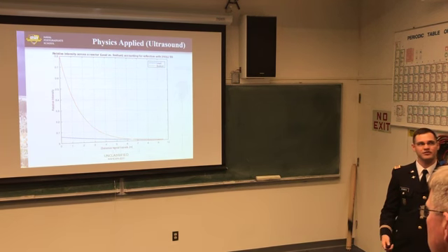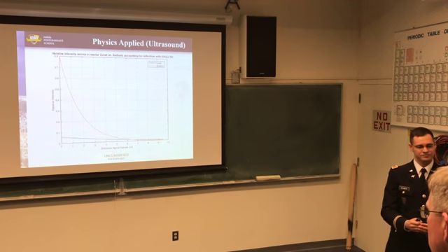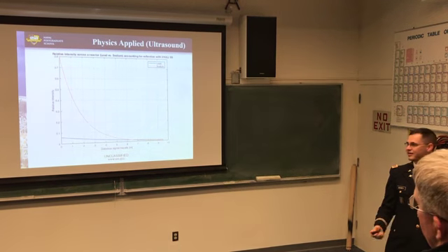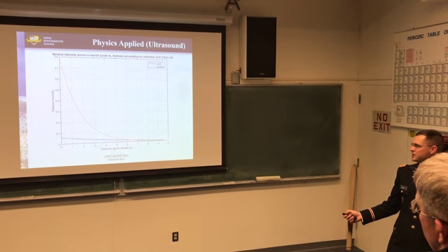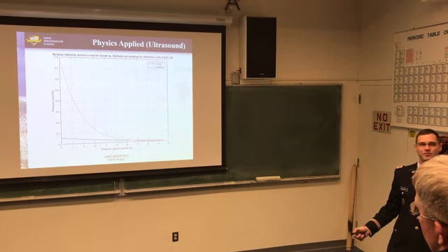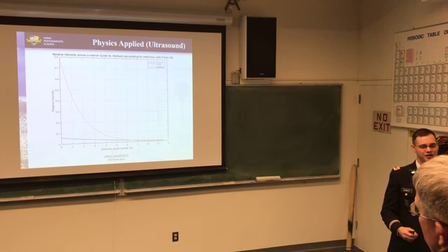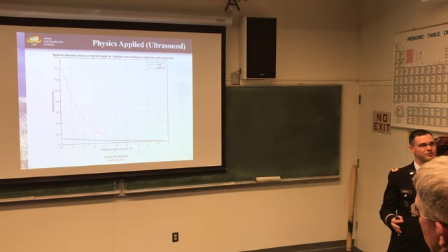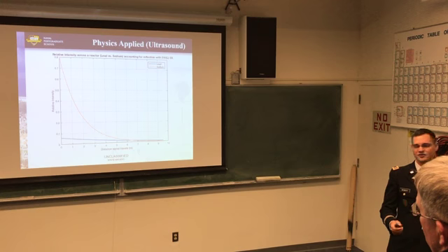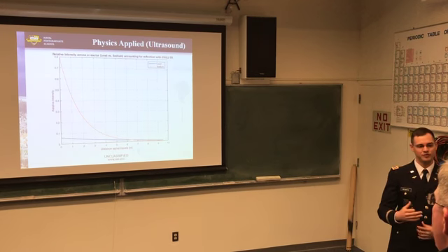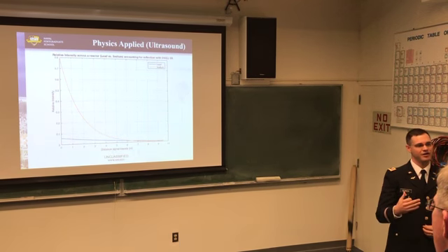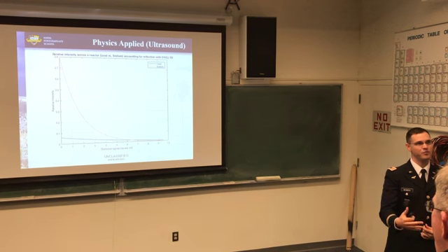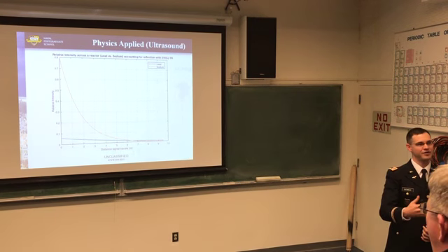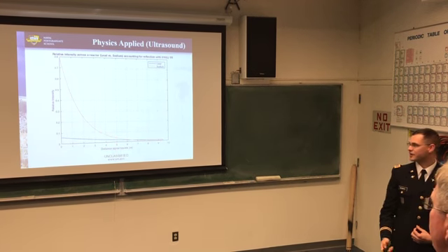So over our typical reactor size, you would actually get more of a signal in lead after about 6.5 meters, which sodium reactors are also about 3 times larger than lead-cooled reactors. So signal over the distance of your reactor, you get more reflection back after the travel distance is taken into account.